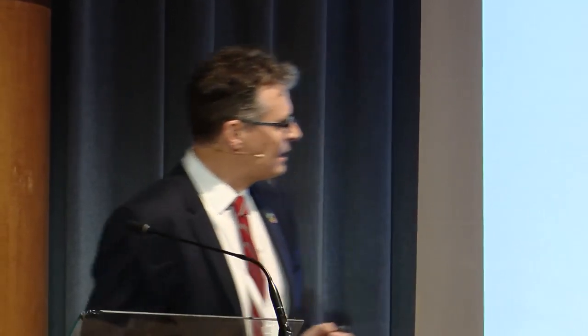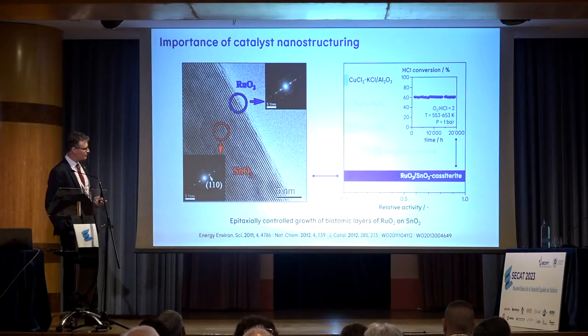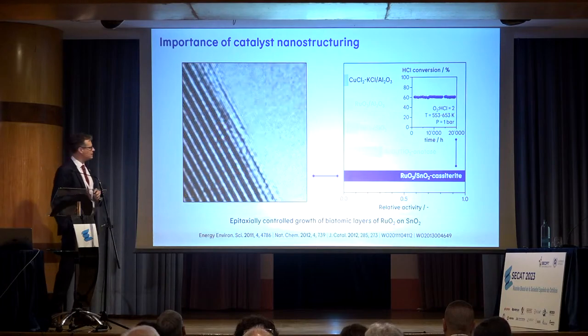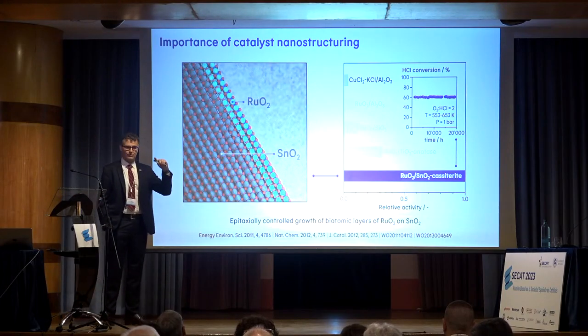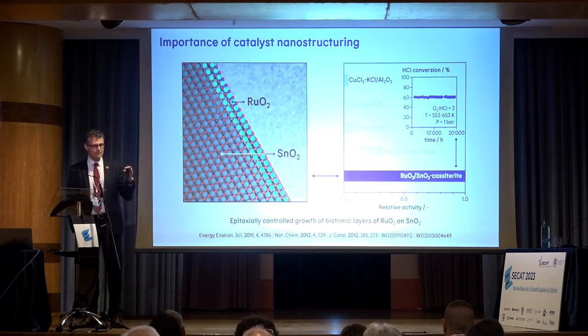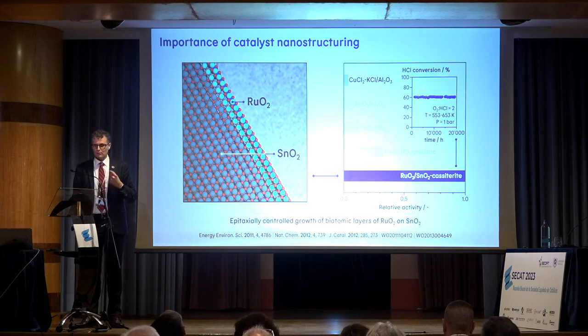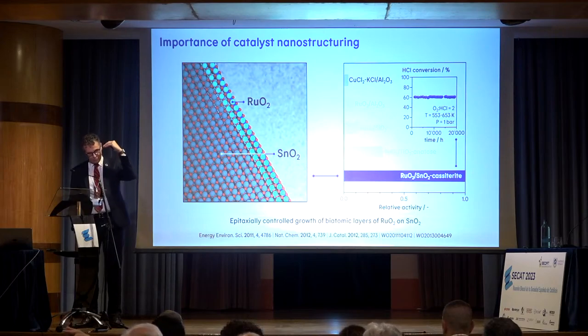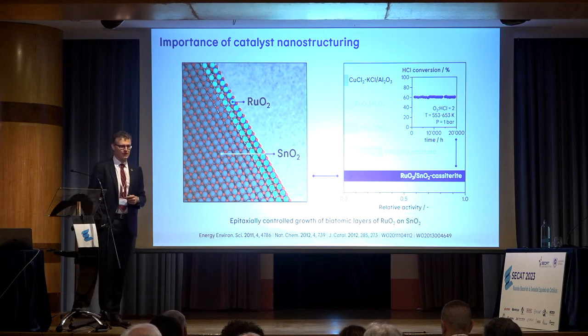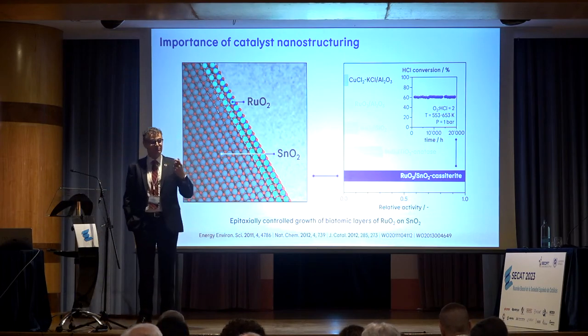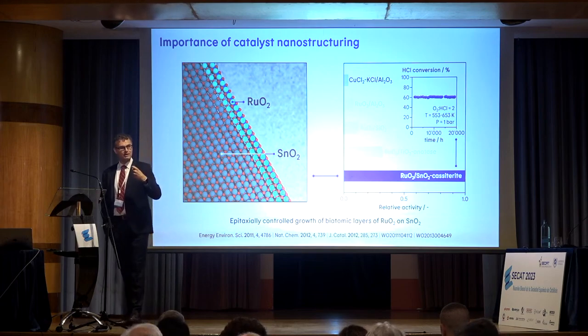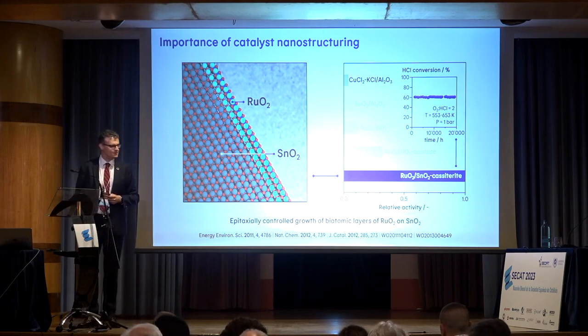Now, this image of the ruthenium oxide on tin oxide shows that this was not just a video, it's a reality. And you can see on the outermost layer of the surface of the catalyst, 2 layers of ruthenium oxide on tin oxide. And 2 and not 3. 1 layer won't work. 3 layers is a very expensive catalytic material. 1 layer doesn't work because of a strong active phase support interactions, which will render inactive catalyst. So you have to put another isolating layer in order to make 2 layers. 3 layers, you are wasting 1 layer of a very expensive metal. And that's the level of precision that you require to implement a catalytic material in this scale.